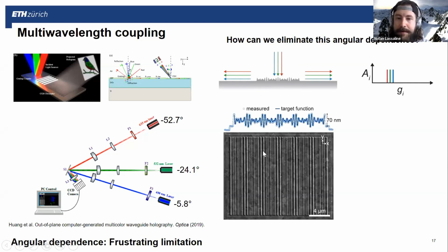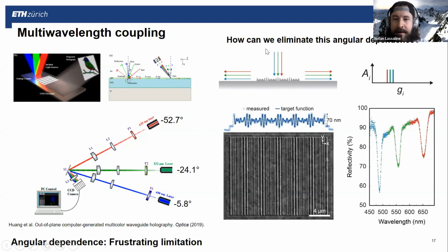And again, we have some complex looking surface that we can only do with the NanoFrazor. And we can transfer this, of course, again to silver. And when we take the surface and shine light on it, what we very nicely see is that this surface is able to simultaneously couple the 3 colors we want, red, green, and blue, shown here nicely with this optical data and their 3 corresponding peaks.